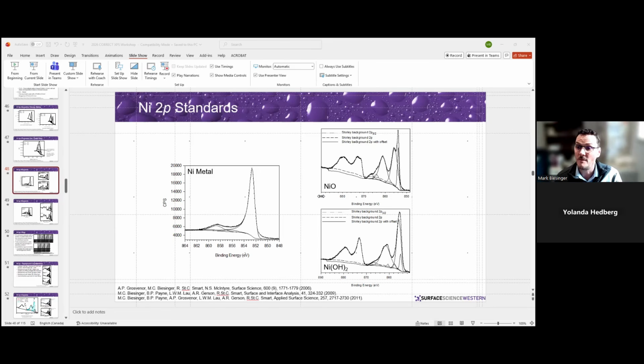These settings are good for depth profiling at a reasonable speed through metal oxides while maintaining chemistry. It depends on your manufacturer, but they would have recommended settings for doing these different types of things that you want to do with the gas cluster ion source. I have to say, the gas cluster ion source is a game changer for analyzing materials. We rarely use a monoatomic source anymore for any of our work.